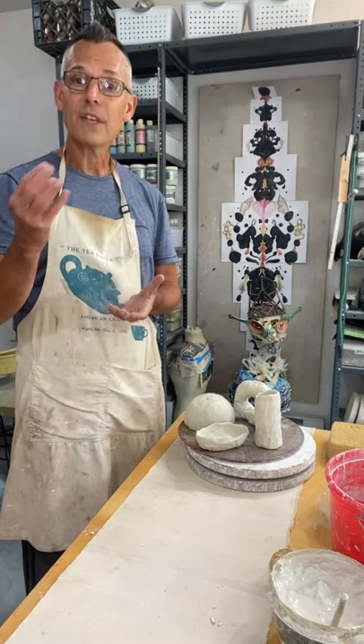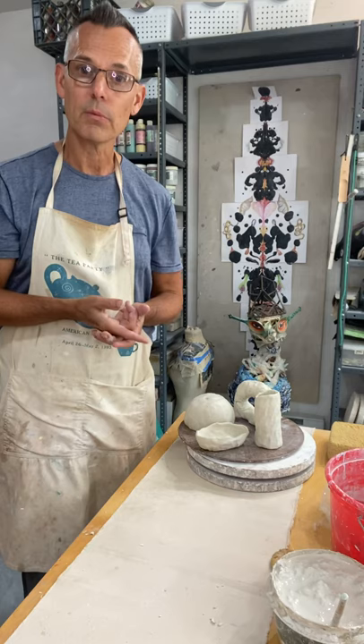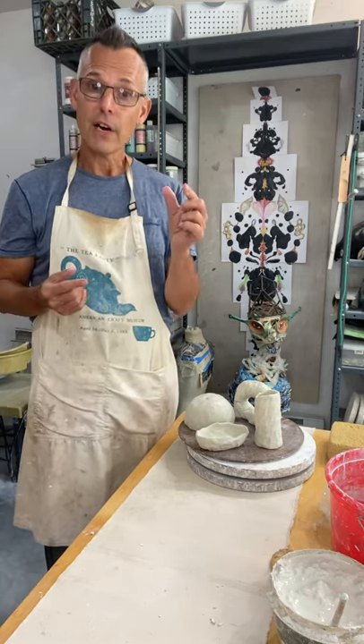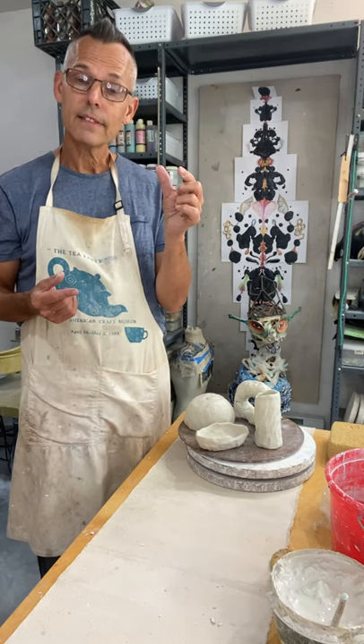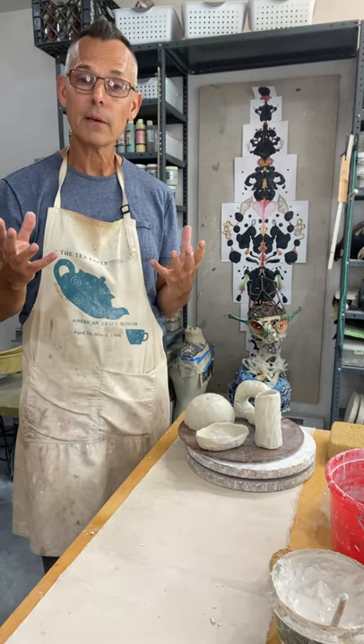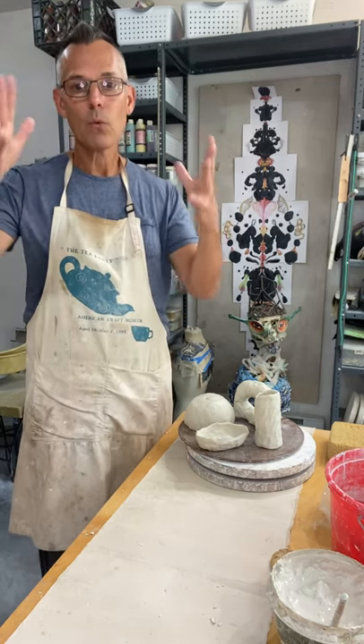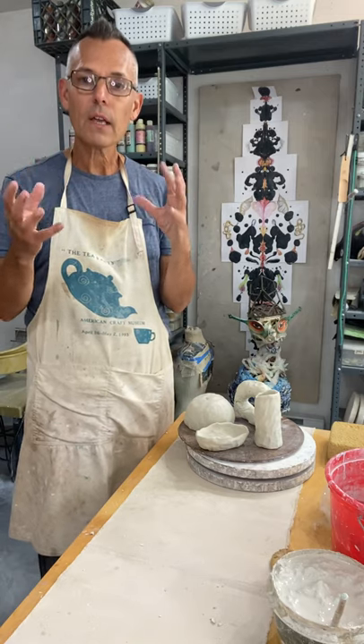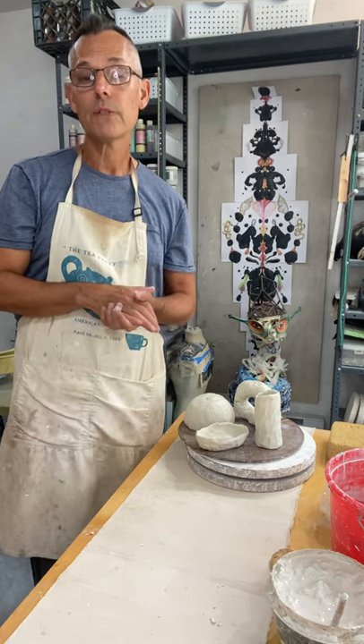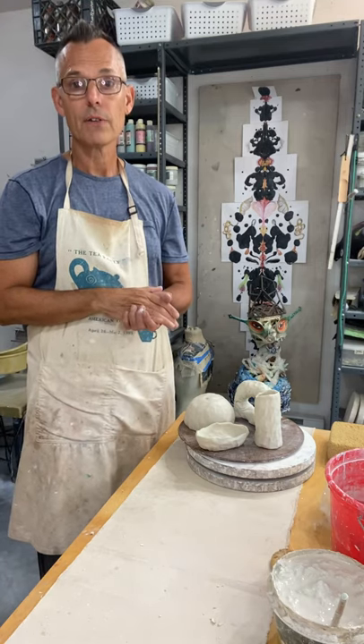It's a great chance to take extra thicknesses that you needed in the wall of your hollow forms away to make them more uniformly even. Remember that thicker areas shrink and move at different rates than thinner areas. So if you have a work that's very complex with thick and thin sections, especially with accelerated drying, you're going to see warping. One reason it's really good to try and envision your work as having one wall thickness all the way through.